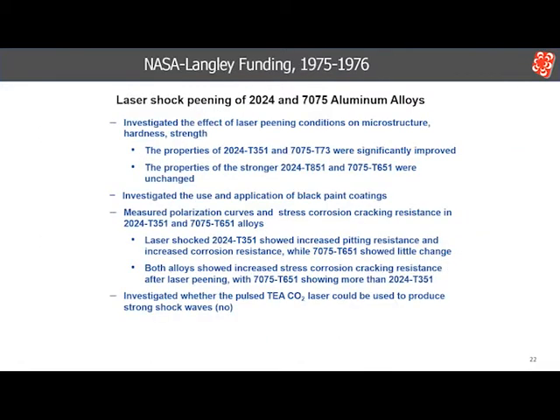In 1975, funding was received from NASA Langley to focus on the effect of laser shocking on 2024 and 7075 aluminum alloys. This included looking at effects on mechanical properties, corrosion, stress corrosion cracking, and black paint overlays. Laser shock 2024 T351 showed increased pitting and corrosion resistance, but 7075 T651 showed little change. Both alloys displayed increased resistance to stress corrosion cracking after laser shocking, with 7075 T651 showing the greatest response. There was also an evaluation of whether the TEA CO2 laser could produce strong shock waves. It could not.